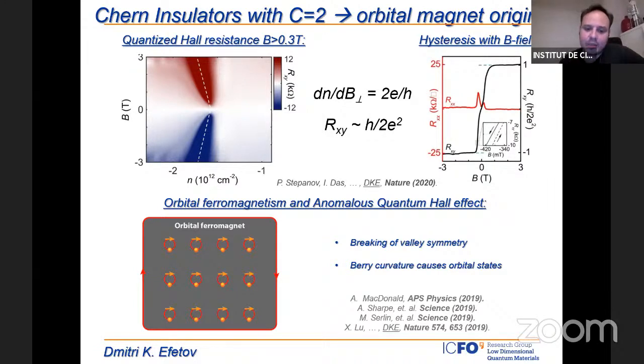And whenever we want to open up a gap between those bands, we need interactions, or sometimes magnetic fields can make band gaps between those bands, and then we observe these quantized Hall conductance regions. Because of often their valley symmetry being broken and the Berry curvature being non-zero, the electrons in these bands behave like they have circular orbits, and because of that, the system is also magnetic. So we really believe now that those are orbital ferromagnets which live in the bulk of the system, and then we also have topologically protected bands on the circumference of the device.